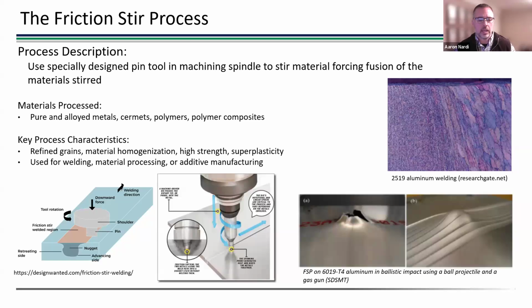And that's where that similarity to cold spray comes in. Now, what's really unique is you get this super fine grain structure, and you can also process materials where you're not welding them together, you're just running the friction stir tool through it to enhance properties like ductility. You see an example in the bottom right here of a projectile being shot through an aluminum plate before and after friction stir welding, and you can see that super plasticity of the material during that impact event.